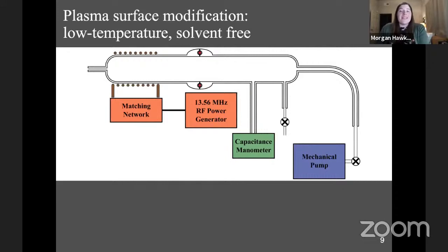And really the precursor can be essentially anything that we can get into the gas phase. This could be something relatively simple, like molecular oxygen, water vapor, short chain hydrocarbons, even more chemically complex things like essential oils. Okay, we can get huge variety in this precursor. Once the precursor has been added, we use an RF power supply to apply power to this induction coil. And what that does is it inductively couples to the gas inside to generate the plasma, that partially ionized gas that's a mixture of neutral gas molecules, ions, electrons, radicals, etc.